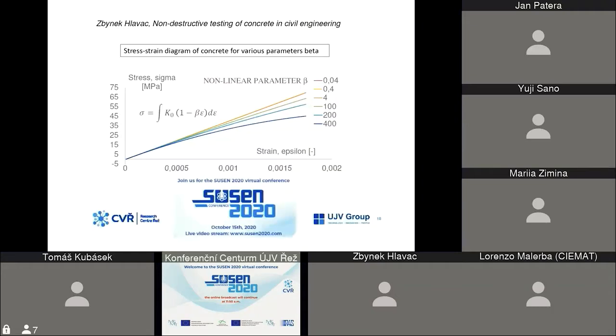Here you can see a graph, which is the stress-strain diagram, with stress on the vertical and strain on the horizontal axis. The higher the parameter beta, the bigger the nonlinearity. So for a linear material, beta would be very, very small, in this case smaller than 0.004. The opposite, when the material is very much damaged, the beta parameter is much, much higher, so that it doesn't behave elastically, but plastically.